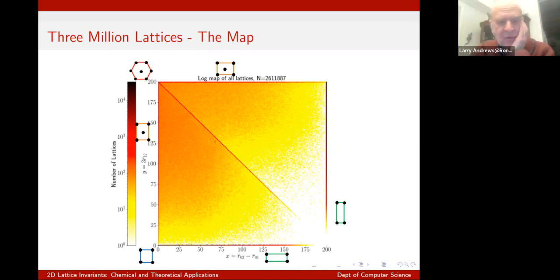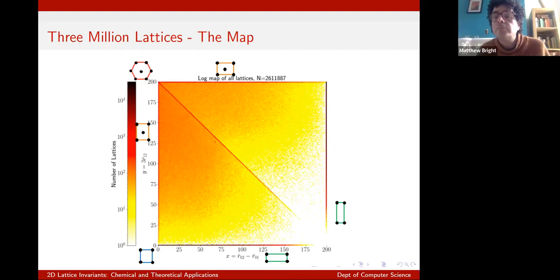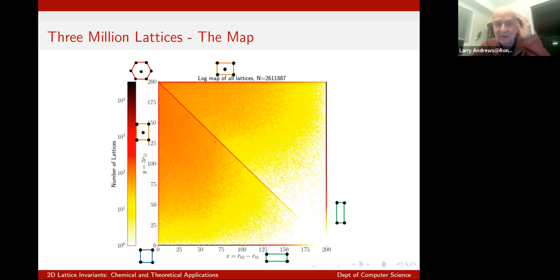Can I make a comment about what you were saying about the gap? A lot of people, when they see an angle near 90 degrees, and I've seen this recently in proteins, make mistakes because they just assume it's 90 degrees. Yeah. Especially in the older data, and there's a lot of that in the CSD, on film, they would just assume it's 90 degrees, and the structure would be solved wrong.